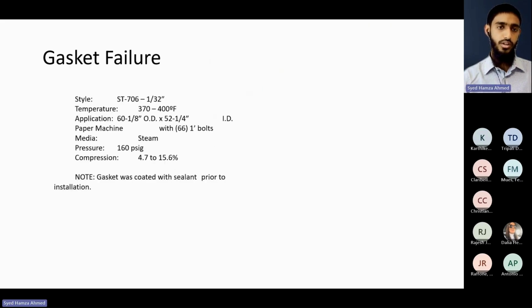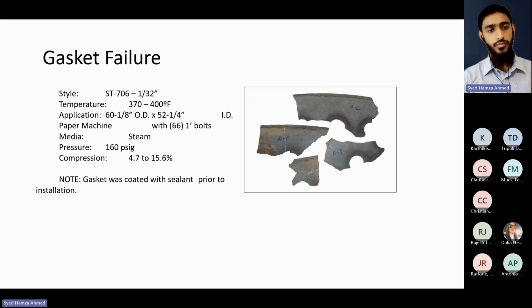We can look at a few examples of gasket failures. Here we have a gasket where the gasket was coated with a sealant before installing it into the flange assembly. Here the proper gasket stress was applied using the proper torquing values. Even then, the gasket got crushed because there was a type of sealant that was used before the gasket was placed in the flange assembly.